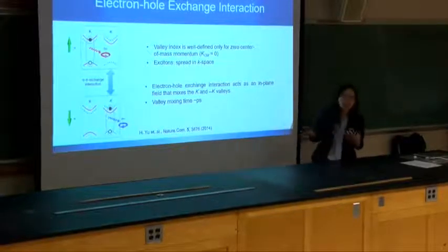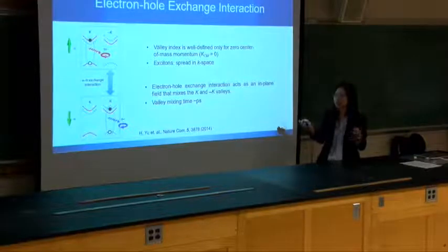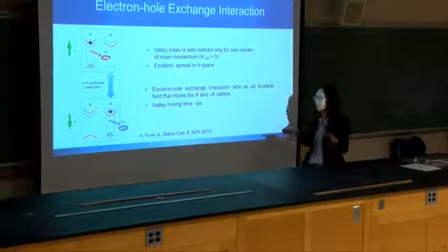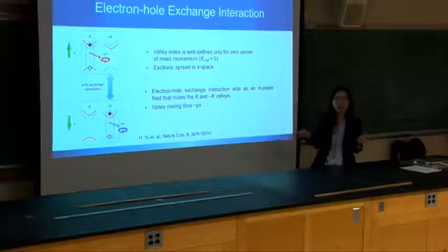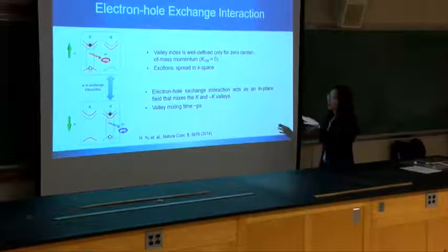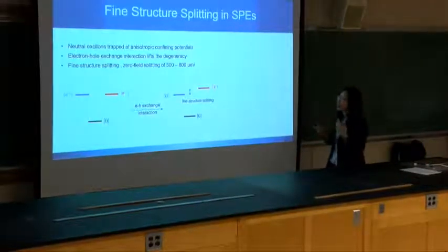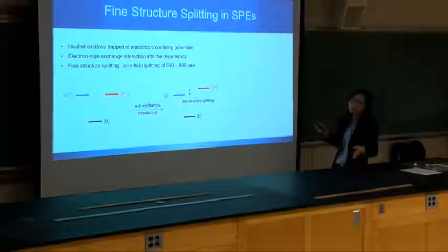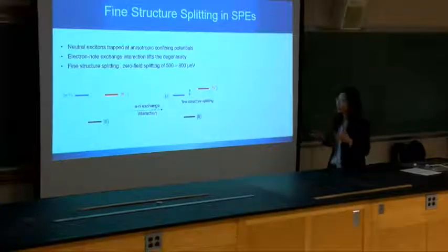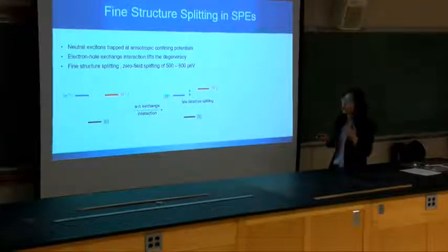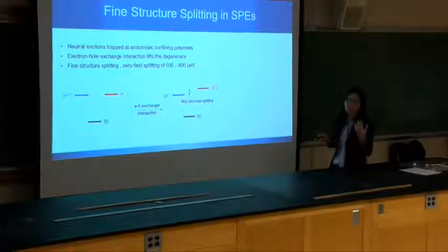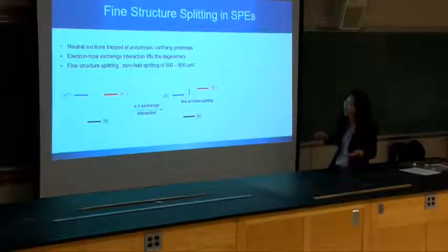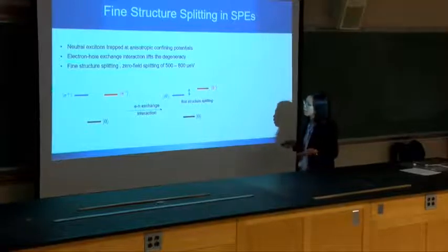And I have to say that this is there no matter whether the exciton is delocalized or localized. The reason we can still see valley polarization for delocalized excitons is because the delocalized exciton has a shorter lifetime. But for a localized exciton or single photon emitter, it has a longer lifetime, and we can actually see this exchange interaction effect from just a simple photoluminescence measurement. So let me give an example here.